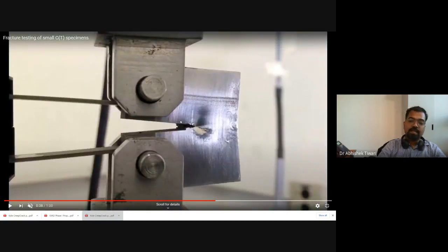So this was loaded cyclically. This was a fatigue test, which is happening at room temperature. But you can do the same thing at high temperature. You can either apply cyclic loading at high temperature, or you can have just monotonic loading, so just pulling, at high temperature. In order to do that, you will have to have a furnace around this specimen. And once you have it, you cannot see the specimen. From the outside, you will only have the furnace, which will be creating high temperature.